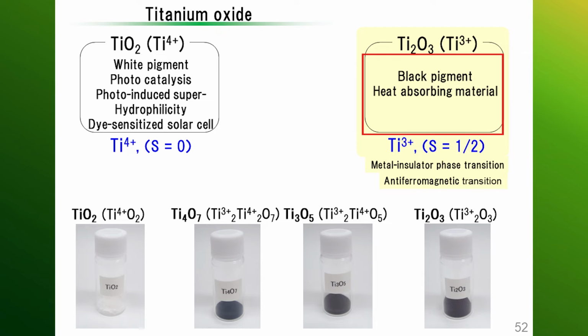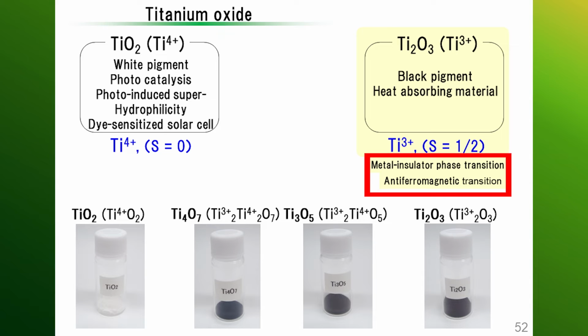It's also used as a heat-absorbing material, and using only titanium tetravalent and titanium trivalent, from pure white to pitch black, we can get such a variety of materials. It's so interesting. And with this material, there is a metal-insulator phase transition, or an electrical transition, or an antiferromagnetic transition, or a magnetic phase transition.